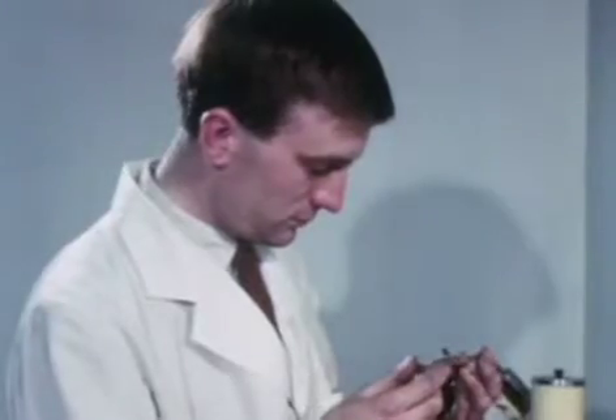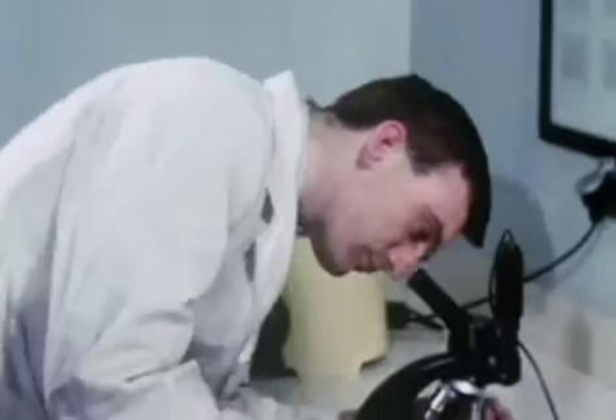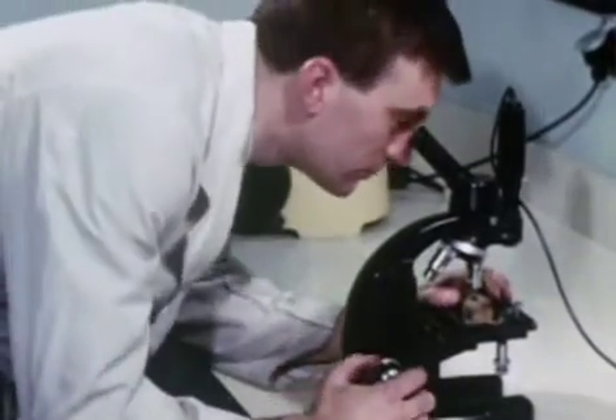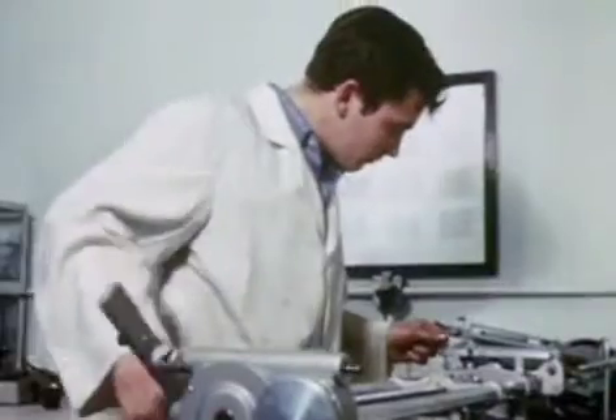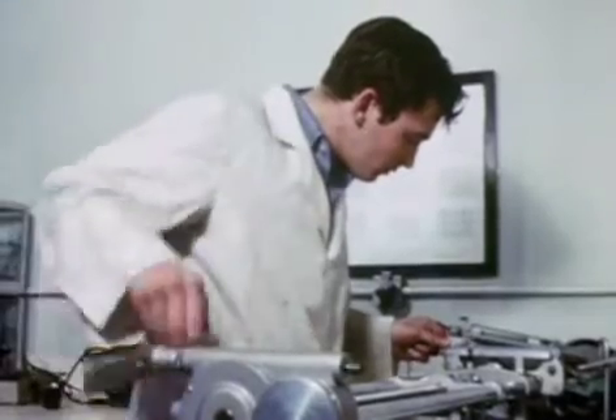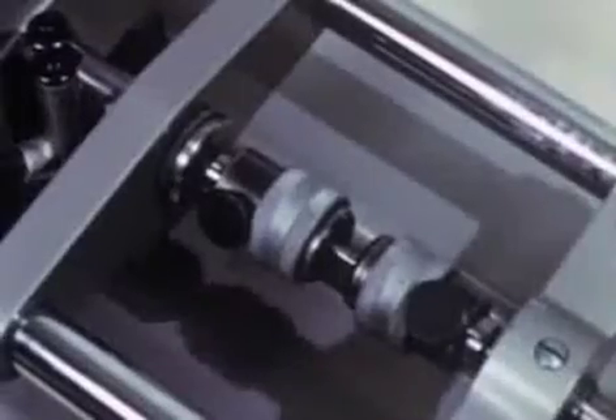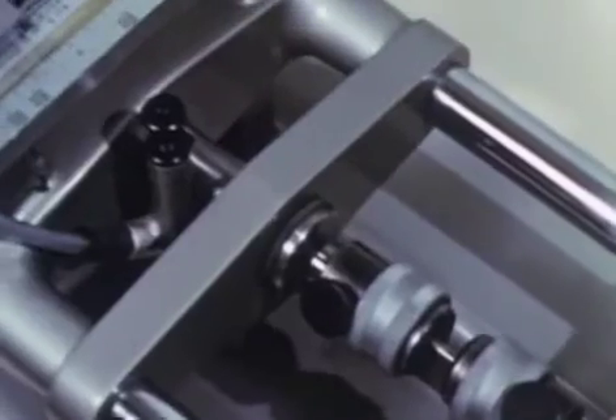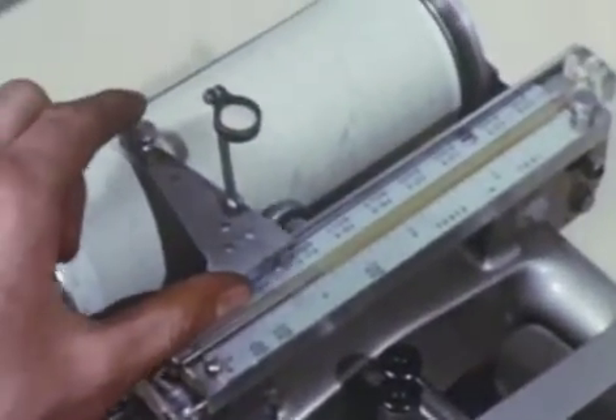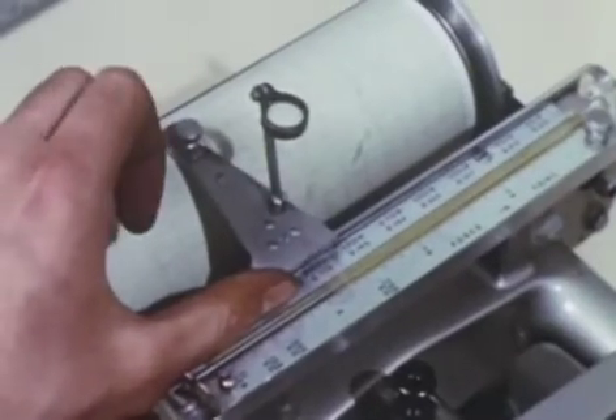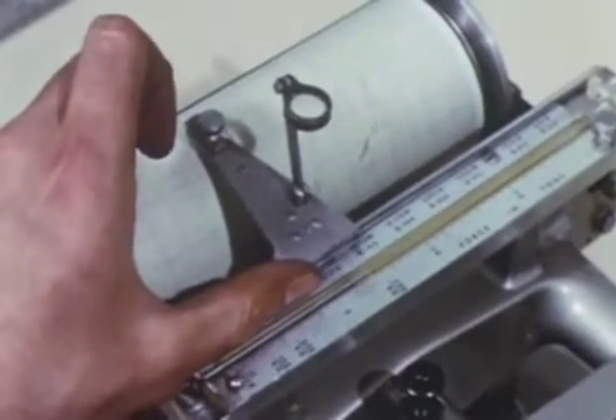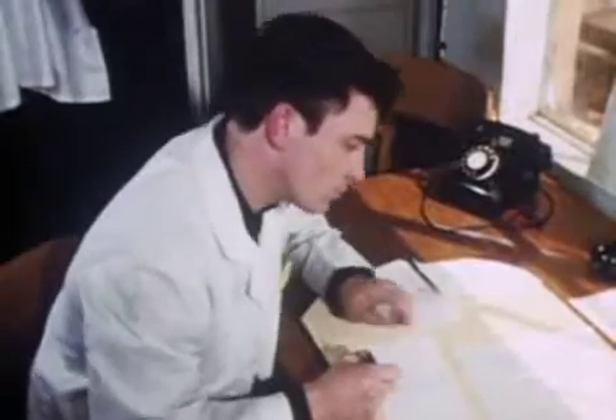A small sample is polished and the microstructure is carefully checked. Now, a test piece is accurately turned and checked on the tensometer to establish that the strength is to the required standard. If the tests fall short of the standard, the casting is rejected. A birth certificate is created for every section so that its history is available for all time.